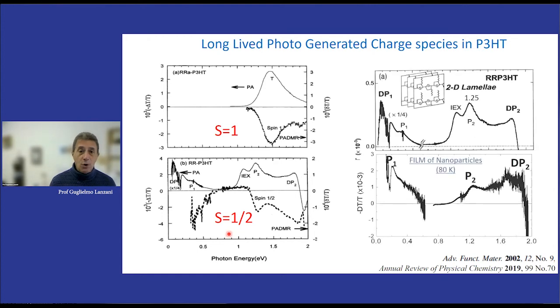So comparing our samples, so these are nanoparticles, this is a film made by nanoparticles deposited on a substrate, you see that this spectrum is very similar to this spectrum. And this one is the spectrum measured by Vardeny in Utah associated to the charged species. So what we conclude is that we generate mainly long-lived charge states. And now, let me go to the mechanism.